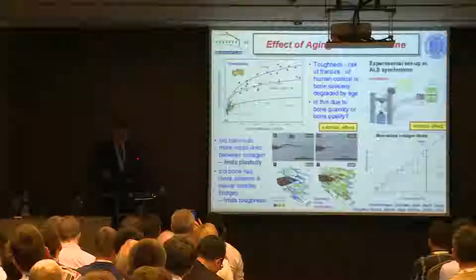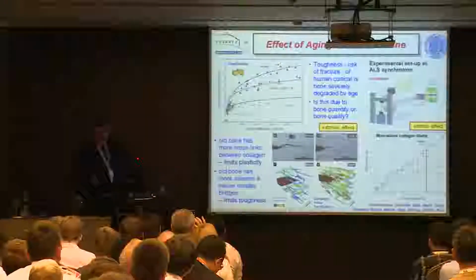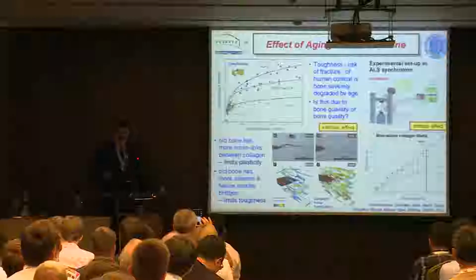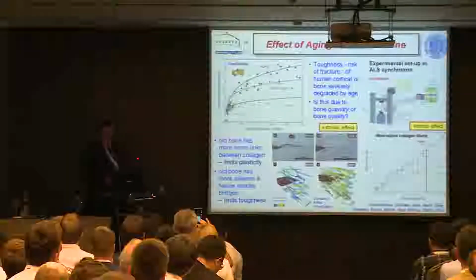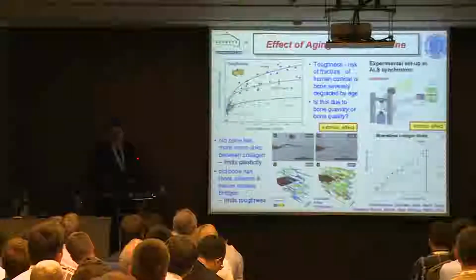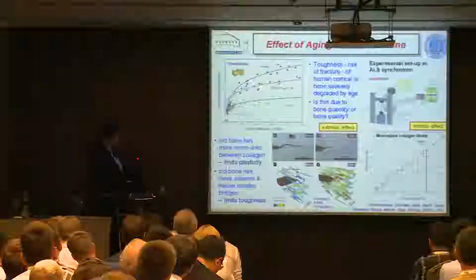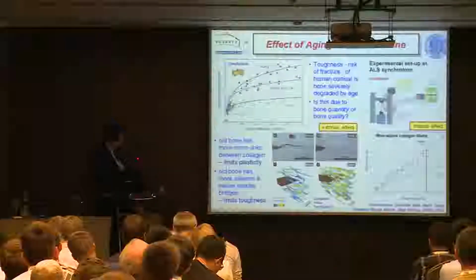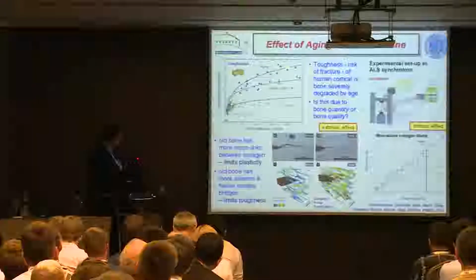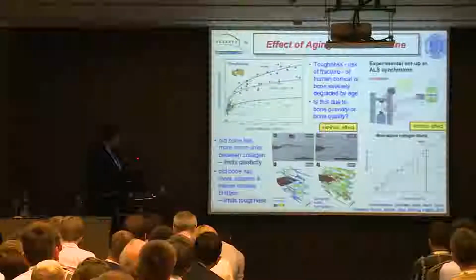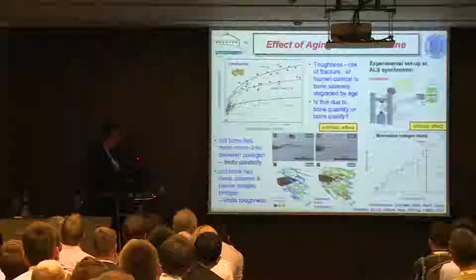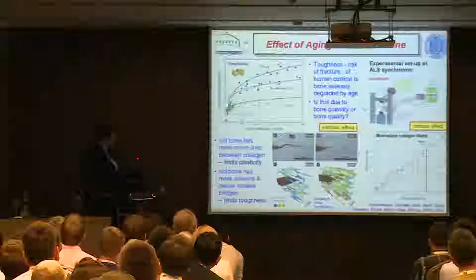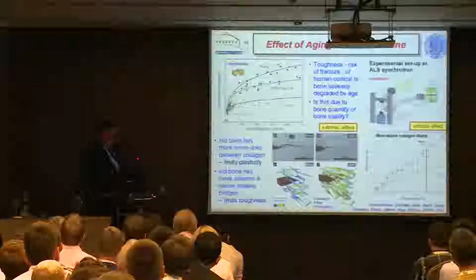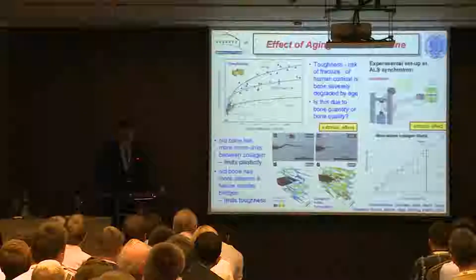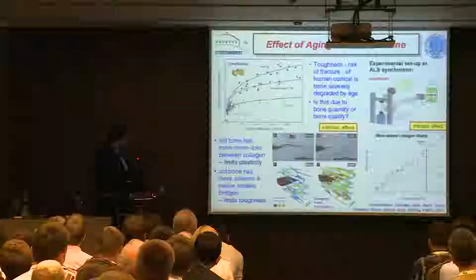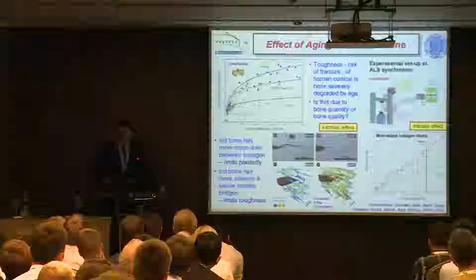A lot of that's thought to be due to loss of bone mass, which is a bone quantity issue, and it of course is, but there's also a bone quality issue as well, which is the fact that the bone deteriorates in its toughness. These are R curves. This is young bone, 30-year-old, 50-year-old, and 80 to 90-year-old bone. You can see as you get older, you don't see this very clearly, but there's a deterioration in the initiation toughness of bone here, and there's a bigger deterioration in the crack growth toughness.